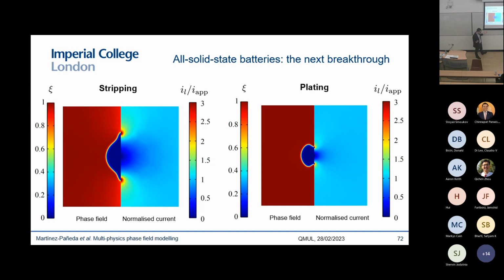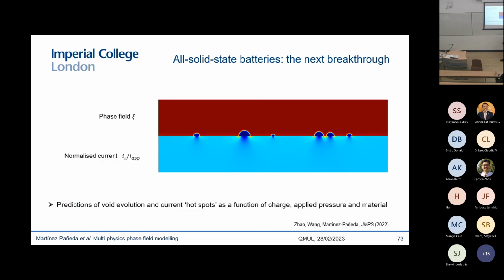And if we do plating, again, we observe the same as we see in the experiments. You can see that the void is closing during the plating cycle, and eventually even detaches from the surface, as we saw in those SEM images from the Oxford group. And of course, we can model more complicated or realistic scenarios where we have multiple voids, you're applying a pressure, so those voids are shrinking a little bit, they're also coalescing with neighboring voids, and you're losing those hotspots, you are eventually killing those voids at some point, and you can do this over multiple cycles